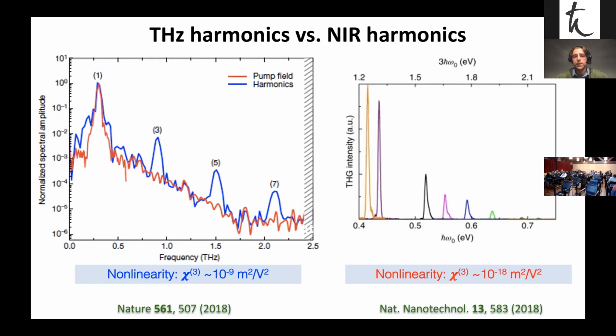And the reason for this is that in the terahertz regime, your hot carriers, this electron thermalization, is enabling this terahertz harmonic generation. Whereas in the visible regime, it's actually working against the harmonic generation. So because of all this thermalization, everything broadens and you get actually a lower efficiency in your nonlinear generation than you would without thermalization.